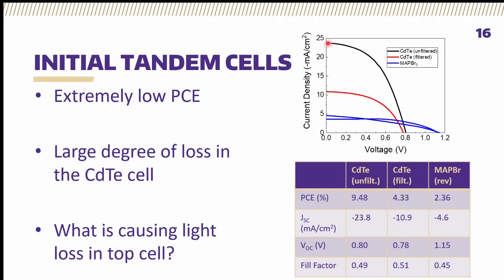But interestingly, we saw that there was another design consideration we hadn't normally accounted for, hadn't expected. And that is this current loss between CdTe by itself without perovskite and CdTe with the perovskite in the tandem. Now, you expect current loss when you have a tandem solar cell. That's just the nature of being the narrow bandgap material. Some of the light you would normally absorb if the top cell wasn't there is being absorbed and converted by the top cell. But the percentage of this light that has been taken by the perovskite is about 50% higher than we would normally want it to be. And so because of this considerable light loss, we wanted to characterize exactly what was going on in this top cell that caused the significant light loss.